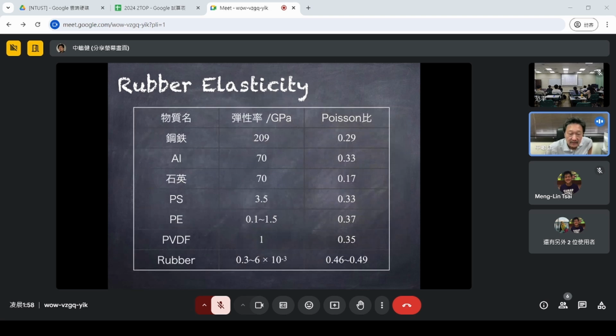This compares the elasticity and the Poisson's ratio for different materials. Metals are at the gigapascal level, and some plastics, polystyrene and polyethylene, also have modulus values on the order of gigapascals. But rubber is 1,000 times smaller compared to other plastic materials. Upon stretching, many materials exhibit a Poisson's ratio near 0.3 or 0.4, which means the volume increases. But in the case of rubber, the volume doesn't change.